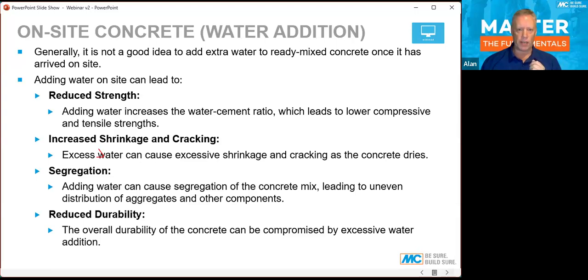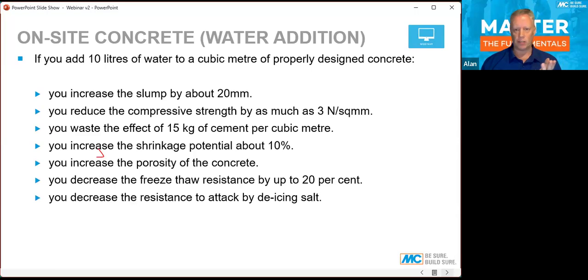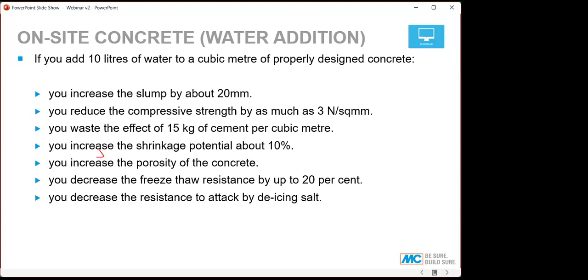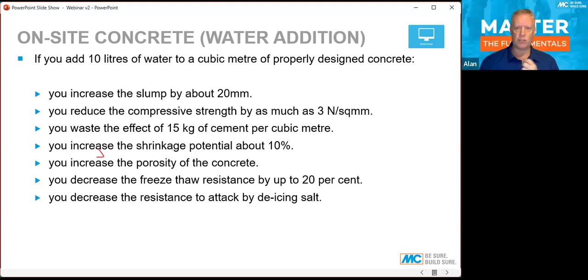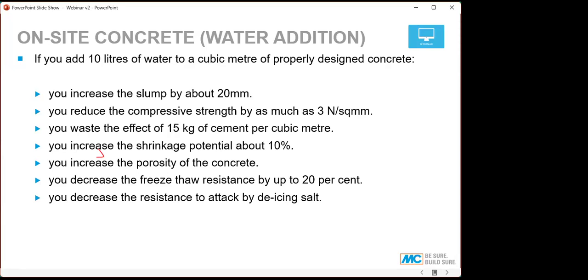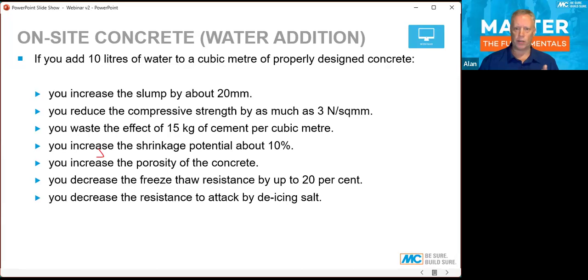So just consider for a minute the effect of adding just 10 litres per metre, just to give you an idea. You increase the slump by about 20 millimetres. That may be good in the case when the workers want it a bit easier to use. But you reduce the compressive strength by 3 Newtons. You waste basically the effect of 15 kgs of cement. You're throwing money away. And you increase the potential for shrinkage, increase the porosity, and decrease the freeze-thaw resistance. So certainly we need to be careful with site addition of water.